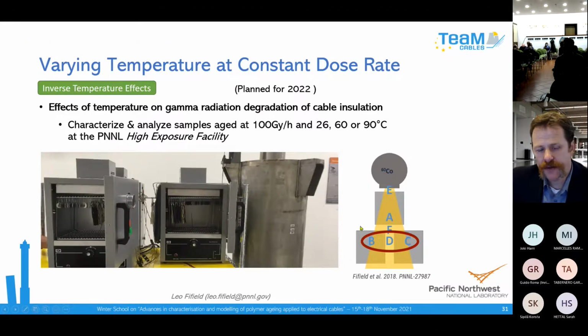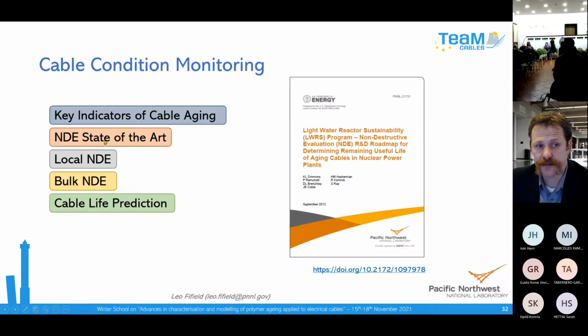So what we're planning to study this coming year is the so-called inverse temperature effect. We have exposed cable samples in our facility here at PNNL with a cobalt-60 gamma source. We exposed 3 different sets of cable samples at 3 different temperatures, but all at a common dose rate: 60, 90 degrees and room temperature, all at 100 gray per hour. We're going to be comparing the effects of a series of different doses on those materials at those different temperatures to look at this inverse temperature effect. So with my 5 minutes left, I will quickly show you the cable NDE task.